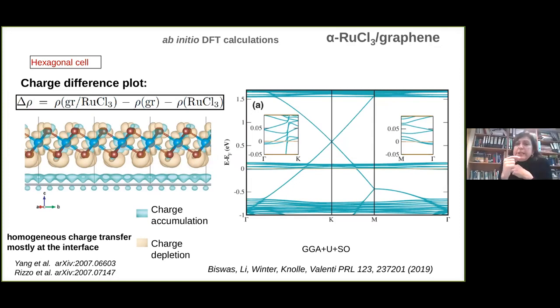So what you want to know is how much charge transfer we are having, right? Yeah, electrons per square centimeter. I do have this number a few slides later. It's not that much. The picture of course looks like a lot, because this depends on which iso value we are plotting. I just chose this iso value because it was representative of showing that the charge transfer is mostly happening at the interface, but I have the number a couple of slides later.